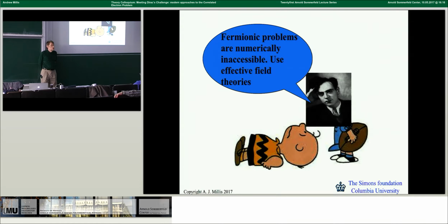But the second thing is that there is a whole interesting field, which I'm not going to comment on here, of, let's say, mesoscopic superconductivity. And in fact, you can still have superconducting properties, particularly for conventional superconductors, even in, let's say, quantum dots which get to be comparable to the size of a coherence length or smaller. You can make very small dots of lead which still have superconducting properties. Right? The key thing you need is that the boundary of your dot isn't pair breaking, that it doesn't rip apart the Cooper pairs. Right? And you need to have, roughly speaking, many electrons comprised within one Cooper pair radius. But you can shrink the thing somewhat smaller than a coherence length and still get superconducting properties.